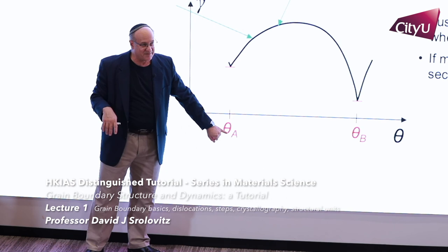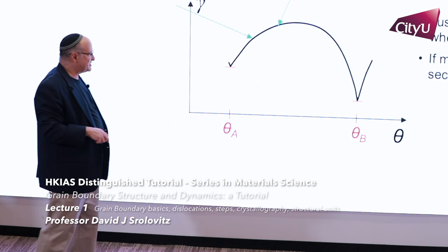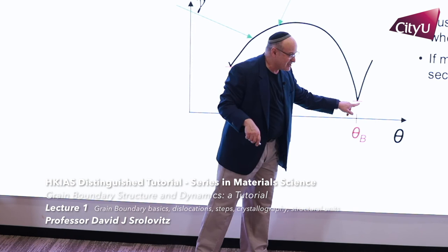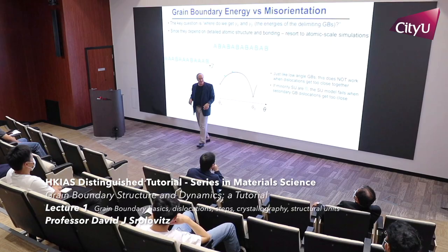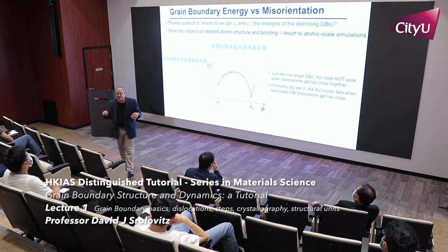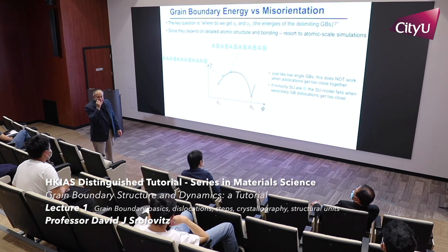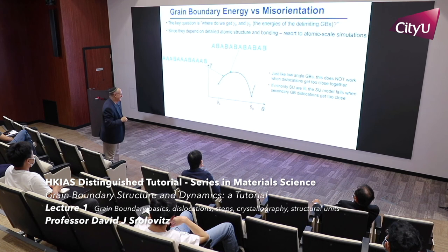Okay? And now if I plug into the elasticity formula, if I know the core energy of this one and the core energy of that one, I can interpolate every place in between using elasticity and crystallography. I don't have to do any other calculations. I don't have to do any other measurements. I just get that. Okay? Now, if you do that, you'll get very bad results. And the reason you get very bad results is the following.